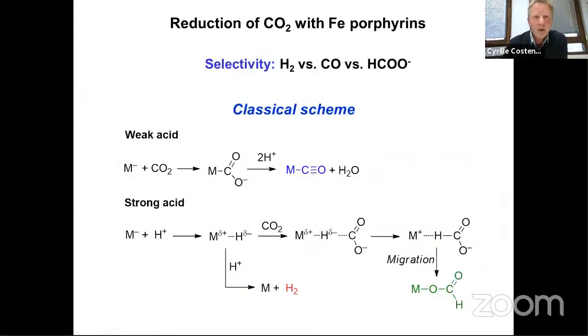Okay, now that we know that iron porphyrin can reduce CO2 into CO, but can also reduce acid, which is a substrate, into hydrogen, we have a competition, okay, between making hydrogen and making CO in the presence of acid and CO2. But we can also maybe drive the reaction toward making formate, because, as I said, in the presence of a strong acid, you first make a hydride, for example, iron 2 hydride, and so you can say, okay, in the presence of CO2, maybe this hydride that accumulates in the diffusion reaction layer can react with CO2 or with the acid.